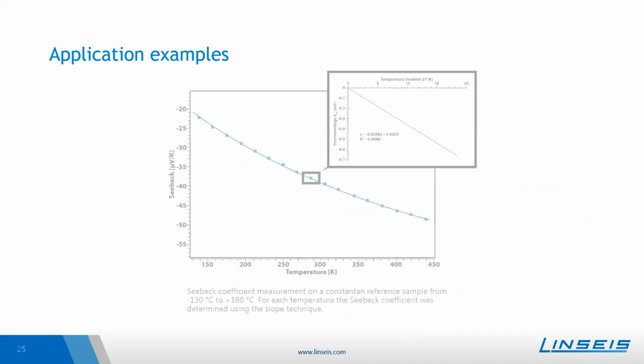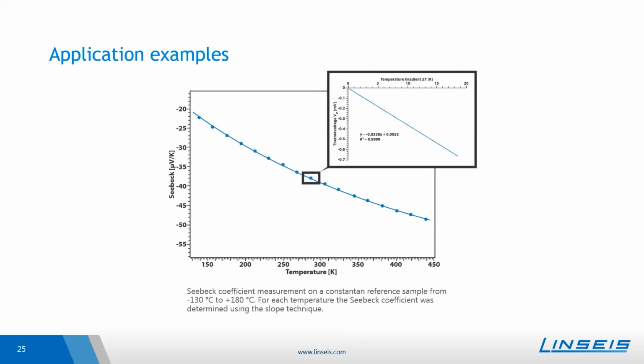system is measuring correctly. And the last example is a Seebeck coefficient measurement, where a constantan reference sample was measured from about minus 130 degrees Celsius up to 180 degrees Celsius. And for each temperature step, which you can see here, the Seebeck coefficient was determined using the slope technique we have seen before. So you see here the temperature gradient sweep where the thermal voltage is measured, and using this linear relation, the Seebeck coefficient was measured.